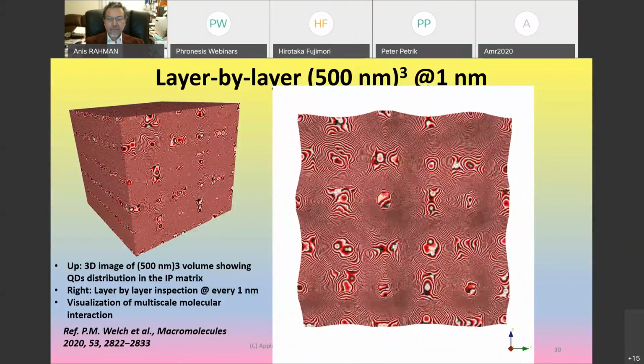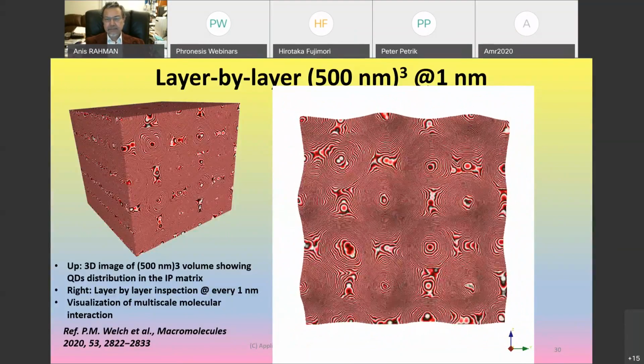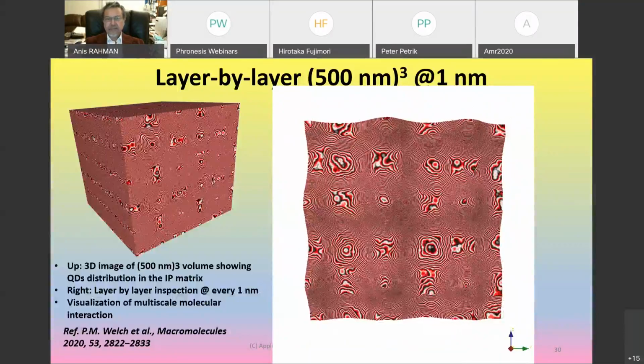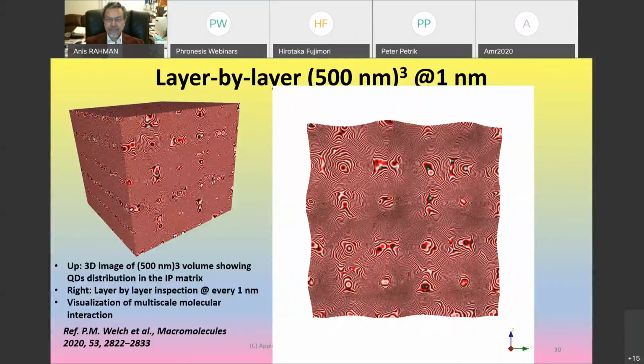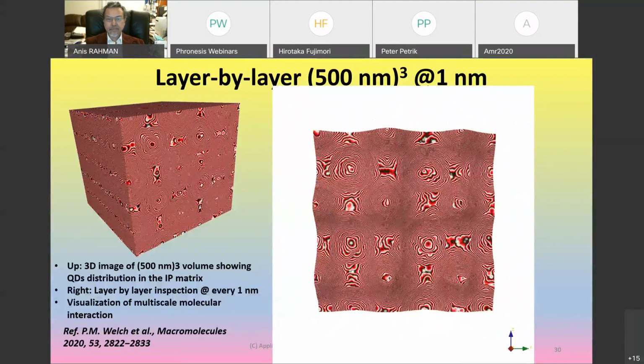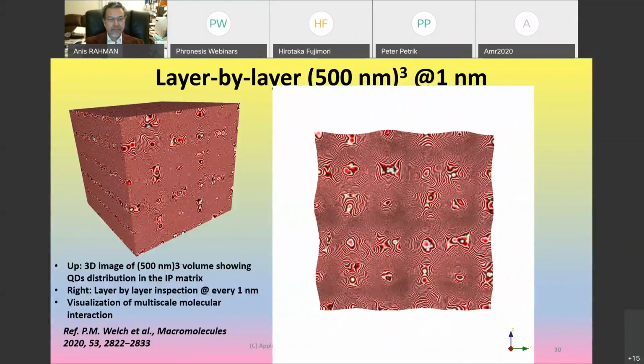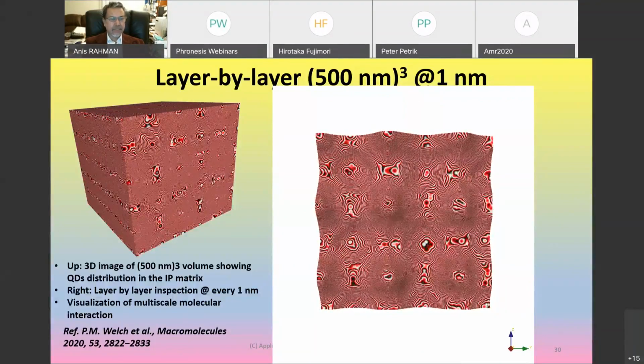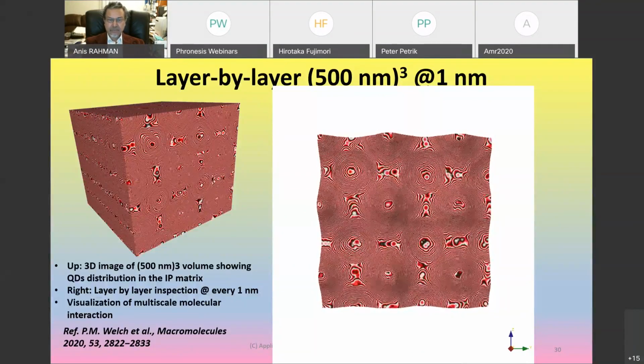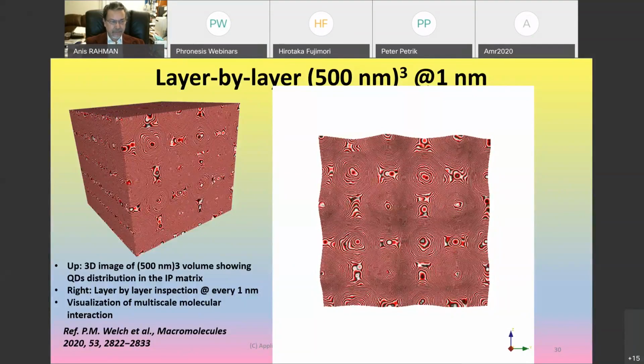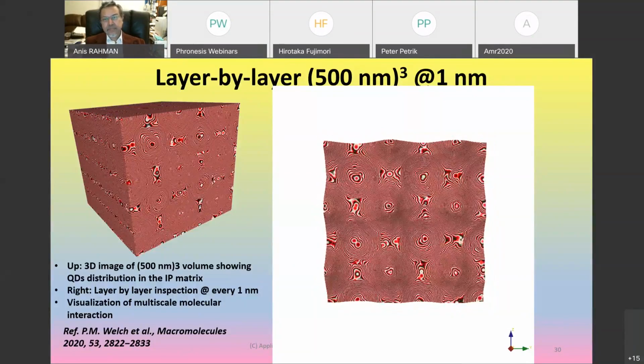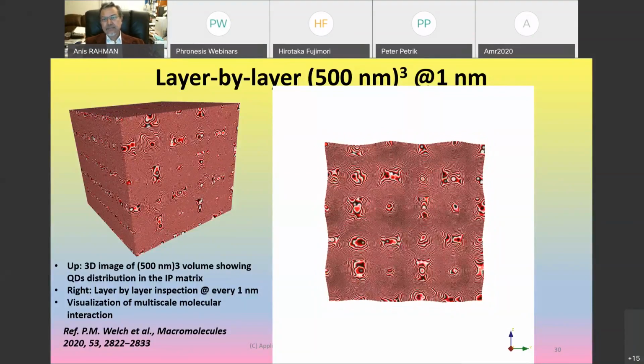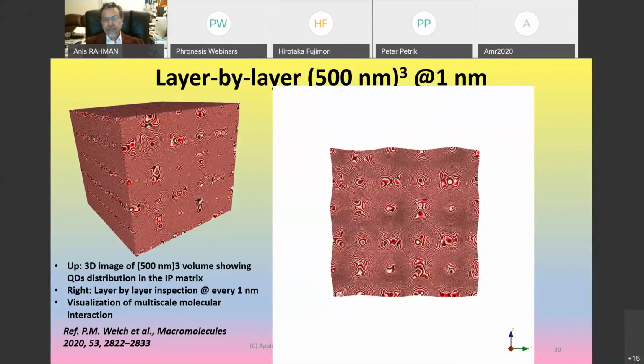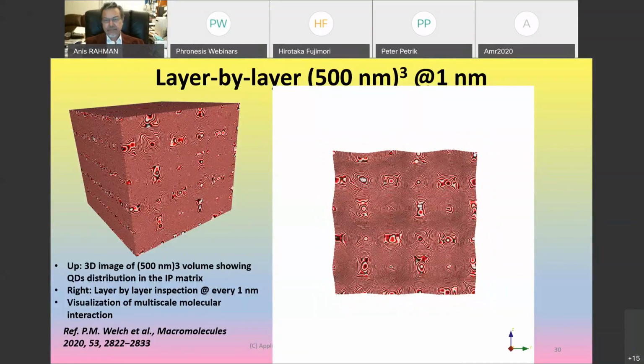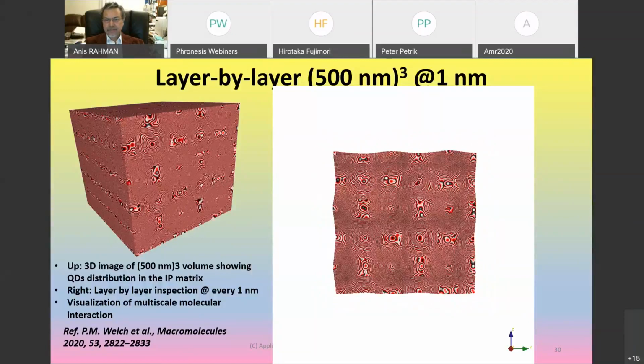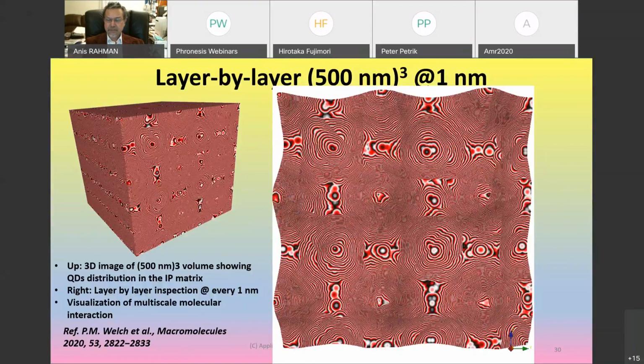For every layer, we can measure the particle size, the polymer orientation, the polymer lattice spacing. As you can see, the spherical layers, everything can be measured, not only at one spot, but at various depths, in a non-destructive way. So these are capabilities that no other instrument can do. There's nothing, AFM, SEM, TEM, or X-ray, or whatever you can think of, nothing can do this except this technique.